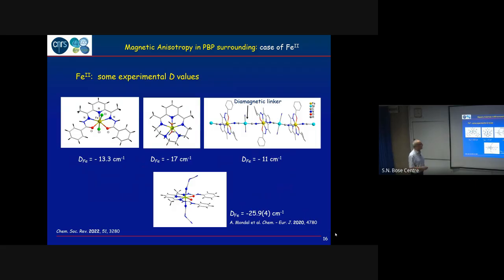So the good news for us was given by comparing these things. So this is what I showed you before. So this is exactly what you expect of this compound. But what happens if you do some chemistry? So here, what we did is we took this compound and we reacted it with nickel tetracyanometallate. So what you do is you replace the chloride by a cyanide that is here linked to a nickel, and the other side goes again. And so this is a chain compound, but the paramagnetic center is only iron. This one is diamagnetic. So there is no exchange interaction, and then it's easy to analyze the anisotropy. And what you can see is the anisotropy found for this compound is the same. So we can do chemistry, the anisotropy is not changed, and the anisotropy is not changed because the geometry remains.